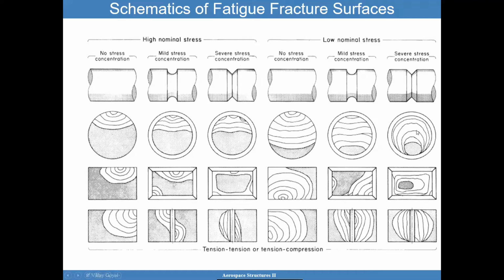So it can get confusing because this one with no stress concentration, high nominal stress, to the very left, compared to this one, looks similar because you could confuse this point and these points as initiation points. But the important thing to understand is that this surface is going to look a lot like this one. It could look very rough, shiny. And if you have a stress concentration, it can help you focus your attention and make you understand that perhaps it did initiate towards the edges, but then it propagated to failure at this point.